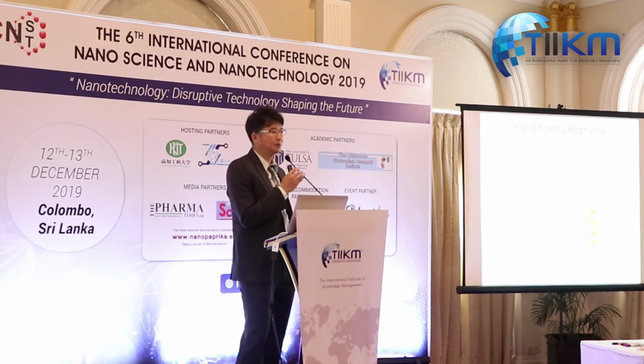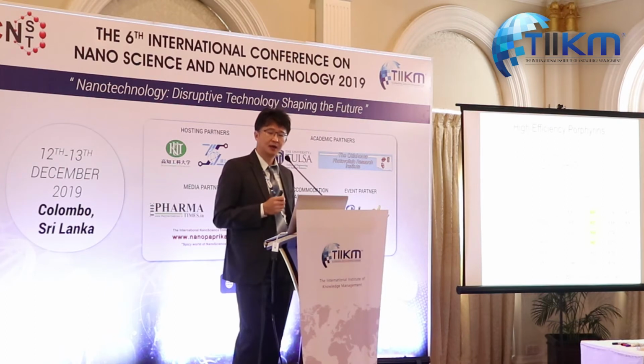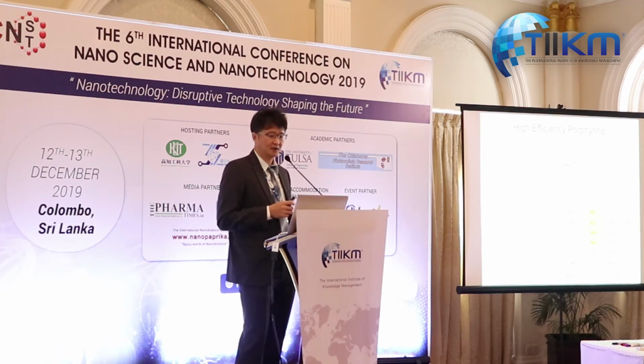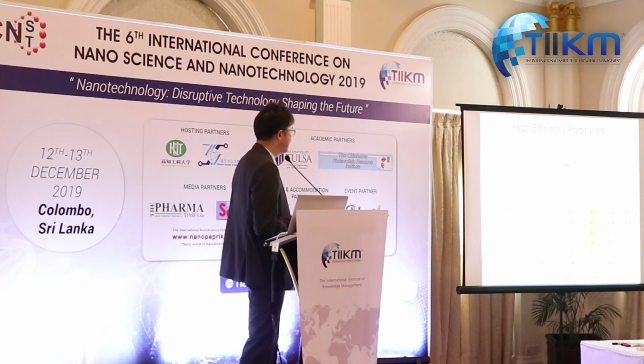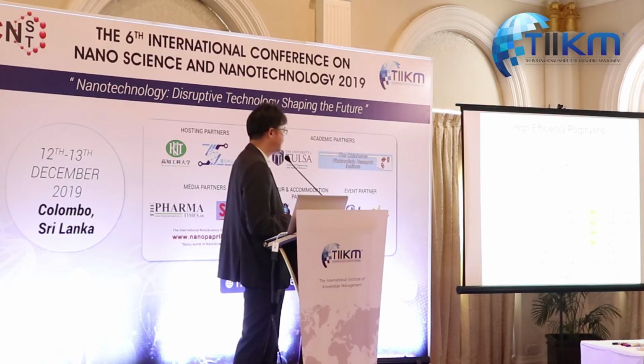Using cobalt(II)/cobalt(III) as the electrolyte, the YD2-oC8 device achieves an efficiency of 11.9%, and when co-sensitized with this organic dye Y123, the device achieves an efficiency of 12.3% under 1 sun illumination and 13.1% for 50% sun illumination.